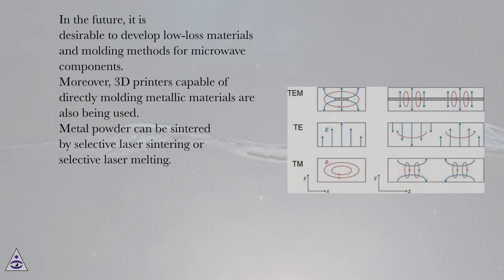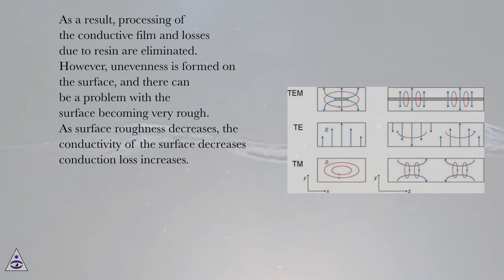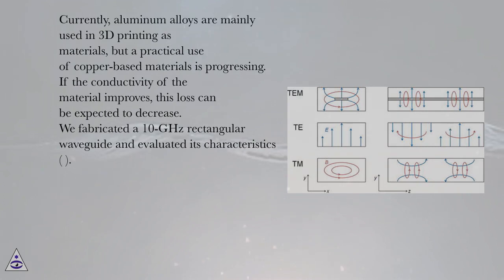Moreover, 3D printers capable of directly molding metallic materials are also being used. Metal powder can be sintered by selective laser sintering or selective laser melting. As a result, processing of the conductive film and losses due to resin are eliminated. However, unevenness is formed on the surface, and there can be a problem with the surface becoming very rough. As surface roughness increases, the conductivity of the surface decreases, and conduction loss increases. Currently, aluminum alloys are mainly used in 3D printing as materials, but a practical use of copper-based materials is progressing. If the conductivity of the material improves, this loss can be expected to decrease.